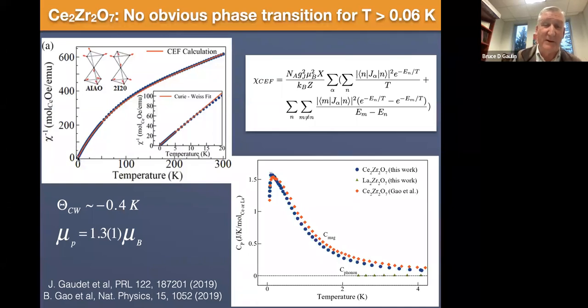So actually we can account for this curved inverse susceptibility more or less completely with crystal field analysis. And that's what's shown in red. But interestingly, what we measured in the low temperature heat capacity turned out to be very useful. And actually, these are two measurements on cerium zirconate. The one in blue is from our group, and the one in red is from Pencheng Dai's group. So completely independent, on completely different samples, different people doing measurements in different labs.